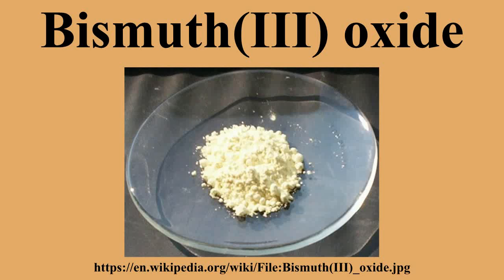This is done in an electrolyte of bismuth compounds that is also rich in sodium or potassium hydroxide so as to have a pH near 14. Conductivity. The alpha phase exhibits p-type electronic conductivity at room temperature, which transforms to n-type conductivity between 550 degrees Celsius and 650 degrees Celsius, depending on the oxygen partial pressure.